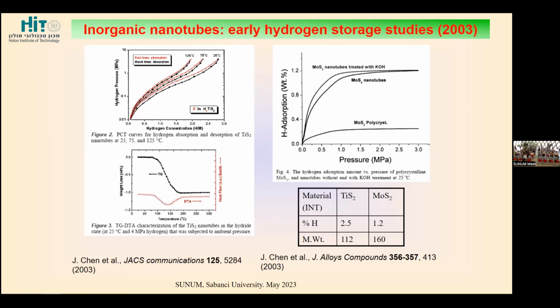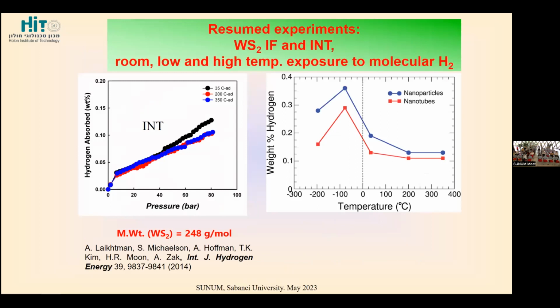So as I have just told, we're not the first who tried to use them for hydrogen storage. There was a Chinese group in 2003 who already published some results of hydrogen storage in this or similar types of nanotubes, either MoS2 or TiS2, and they achieved some results by different methods, though these results were not verified by precise techniques. But they very fast discontinued their research for the same reason that I have just mentioned, that in 2003, these materials were not available in more than milligrams, so there was no interest from industry for their applications. And we decided to resume the experiments about 9 years later when this problem was resolved.